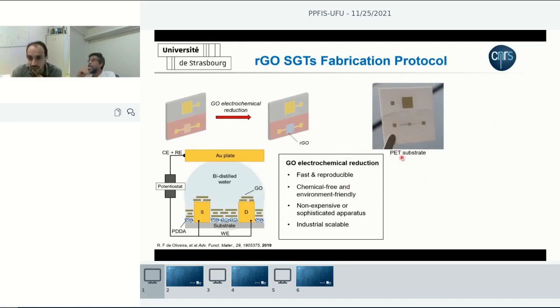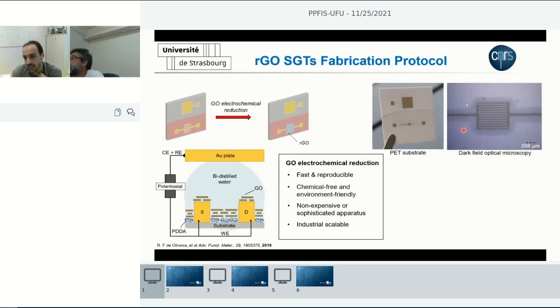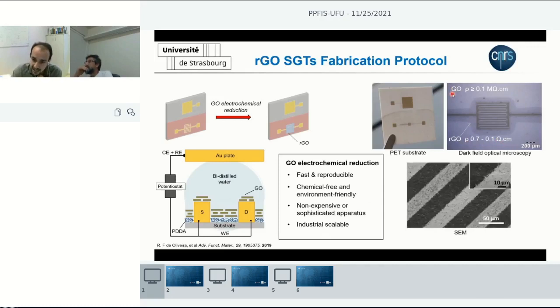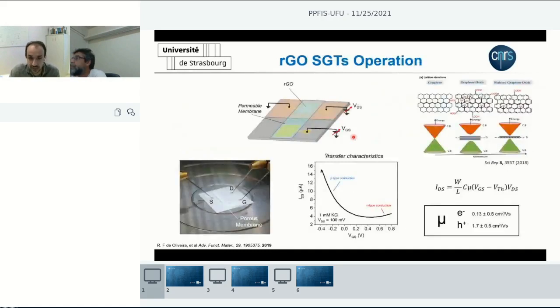Here's a picture of the real device on plastic, and you can see the contrast between these two regions, where here we have the interdigitated source and drain electrodes. This region here is the graphene oxide region, and the slightly darker region is the reduced graphene oxide, which has a much lower resistivity than the graphene oxide. And this can be used even on such a rough surface as plastic ablated by a laser. So it means that this kind of film covers even very rough surfaces. I think the roughness here is pretty high, more than 50 nanometers perhaps. And the method is compatible with several different types of substrate, as I told you.